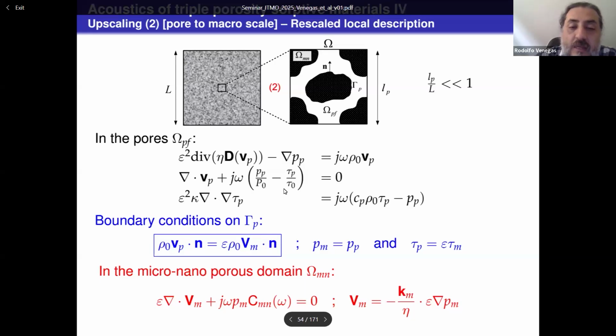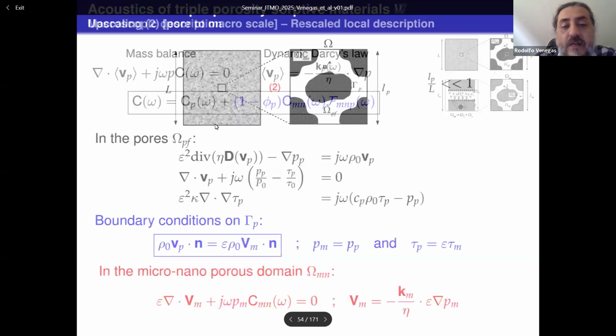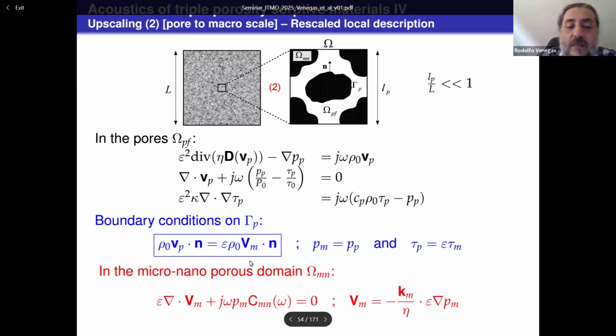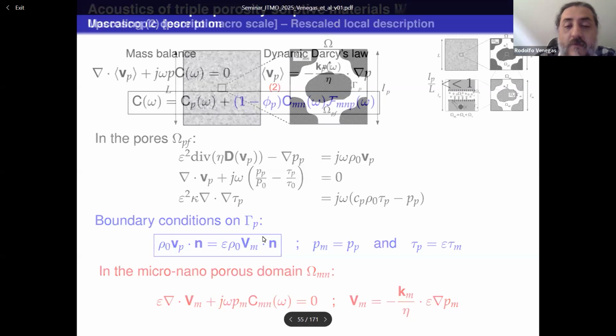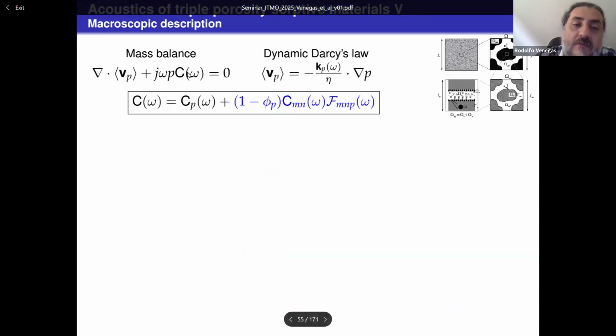in these pores. We solve the problem, and because we get very similar problems, Stokes problems, and then Fourier's problem, and when we identify the mass balance equation at the linear order, we take the average, we end up with this description that is also of an effective fluid, where the permeability is determined purely by what's happening around the grains. But the compressibility has one component coming from this part here around the grains, plus the compressibility of the grains itself, this CMN, and this pressure diffusion function that is accounting for the multiscale or interscale coupling.